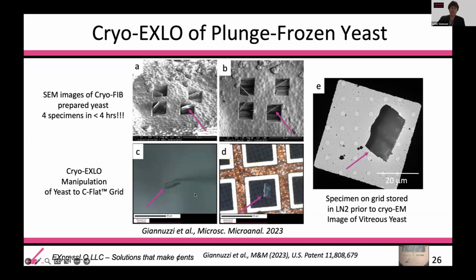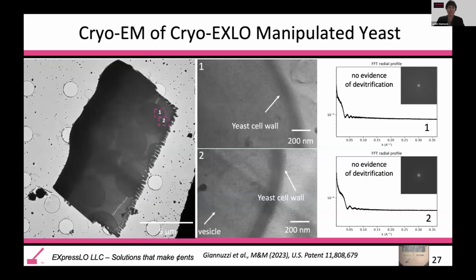We manipulate it to the cryo-exlo station. Here's the specimen on the grid, and then, specimen on the probe, and then the specimen on the grid. Here's a low magnification TEM image. And then, of course, here's our, again, further evidence, higher magnifications and FFTs showing no evidence of devitrification.